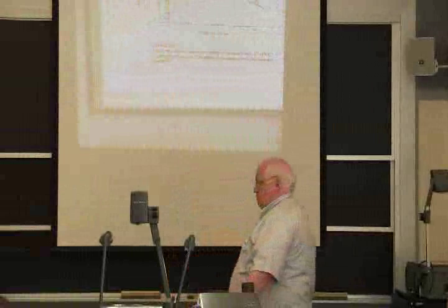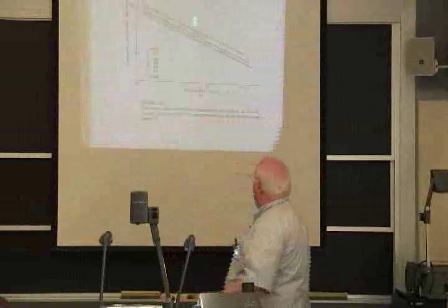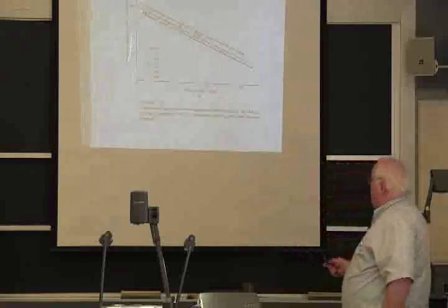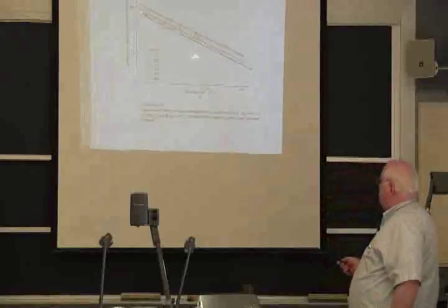It turns out, if you look at the primary dendrite arm spacing, this plot's versus cooling rate, so it's got a minus 1/3 slope rather than a plus 1/3, but it's just one case you're plotting cooling rate, the other one you're doing local solidification time. And this is a bunch of aluminum alloys, and it shows 100 microns to 10 microns.